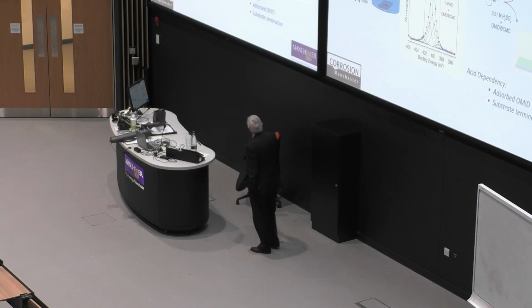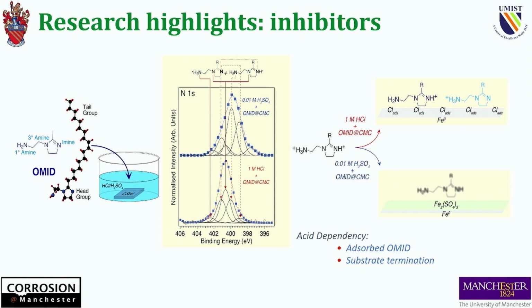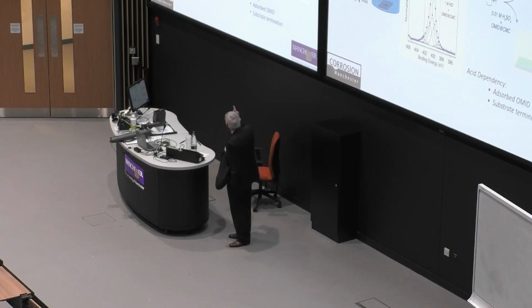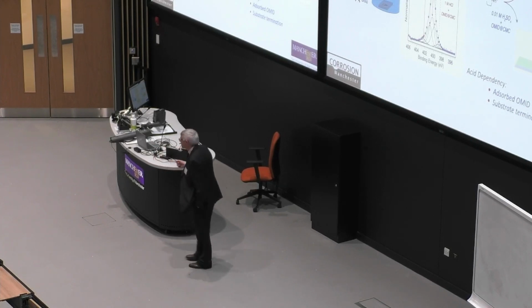If you look here, you'll see that in this case, the inhibitor, which is this stuff here, is basically a head chain, an amine or an amide, and a big long fatty acid chain. In hydrochloric acid, it adsorbs through an iron chloride intermediary, and in sulfuric acid, it kind of maybe does or doesn't adsorb, but onto a ferric sulfate surface. So it doesn't really inhibit in the way you imagine it inhibits in the first place. Only by understanding this very, very precise detail can we begin to develop inhibitors which will function in a designed way, rather than just we'll try it and see, no, it doesn't work. We'll try it and see, no, it doesn't work. And after 100 tries, you might get one that might work. Same thing with paints.